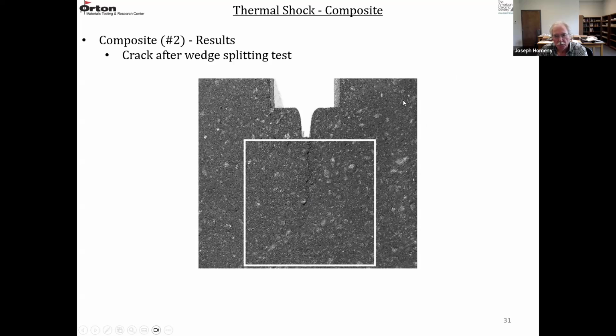It's pretty gray in color. That's because of all the carbon present. You can barely see some of the MgO aggregates, the lighter areas. This is the crack that's propagated. So this is the sample after the wedge splitting test.